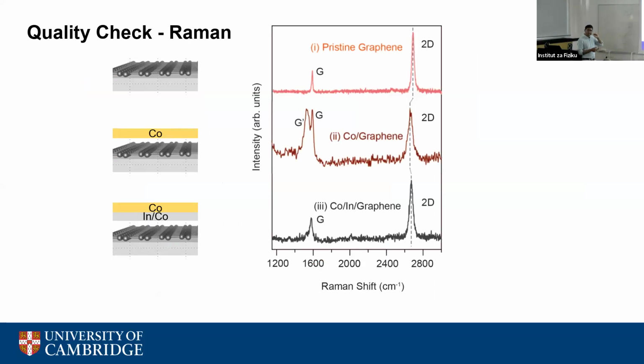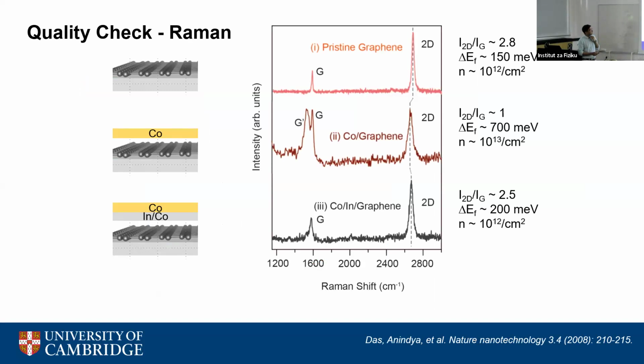You can deposit very thin electrodes, and you can measure the Raman from the top. This is the Raman spectrum of graphene, which has two characteristic modes related to its band structure. If you deposit cobalt, we see that this mode splits up and gives rise to a very strong defect mode, which is related to chemisorption of metals. Some people have shown that from this Raman, you can calculate the change in carrier density of graphene as well.